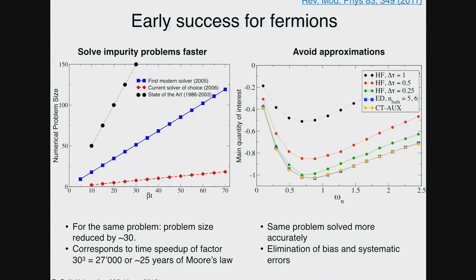What you see is that back in 1986, the state-of-the-art algorithm, which at the time was based on a Trotter-Suzuki decomposition, scaled something like this over here. Back in 2005, with an interaction expansion, we were down to a scaling like this. And then in 2006, with the current method of choice, we're down to a scaling that is somewhere here. You see that all of these are linear in beta. But there is a prefactor of about 30 or so between the 1986 method and our current state-of-the-art method.